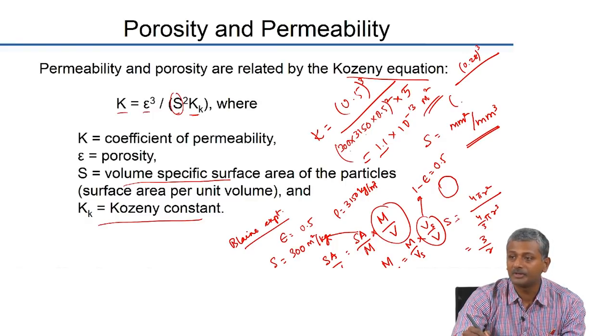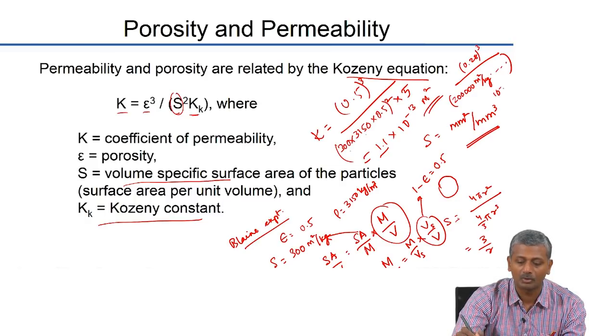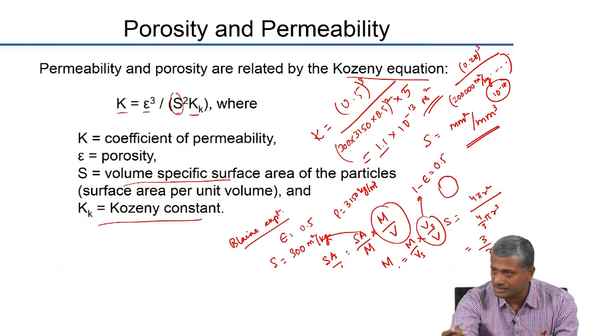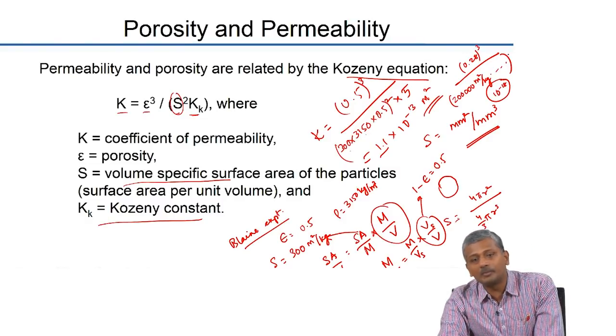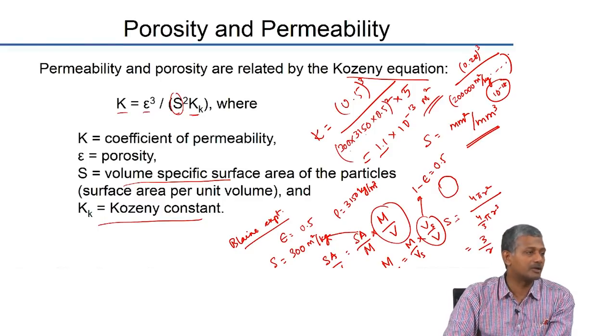We talked about different measurements which lead to a surface area of 200 to 300,000 square meters per kilogram, right? So we are talking about a surface area which is 3 orders of magnitude higher than that of cement. So you can imagine that when you do the same calculation, you may actually get an expression which is going to be of the order of 10 power minus 18 or 10 power minus 20. So CSH itself has a much lower permeability as opposed to this bed of cement particles.